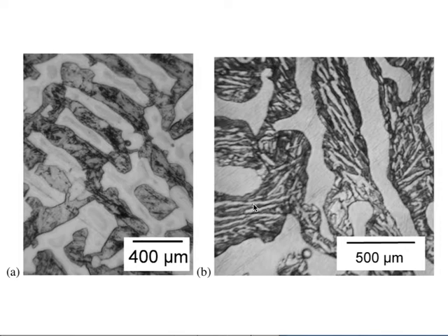So I explained to you that for spot welding, we require the steel to have a low carbon concentration. Otherwise, we get untempered martensite, which will crack. Okay? Now, if you have permanently delta ferrite in the structure, you will never get 100% martensite. So you can now actually play about with increased carbon concentration as well.